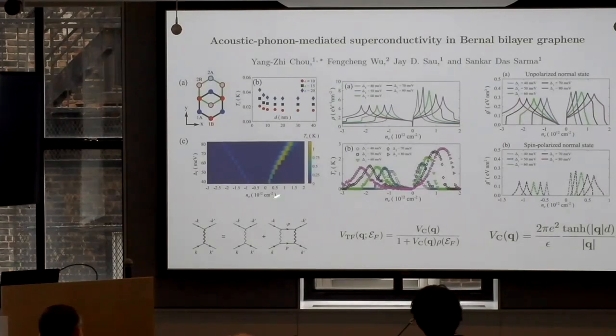Here, with Tc being this low, I insisted that we must include the mu star effect, meaning the repulsive interaction effect. First, there is a screening effect just coming from the gates. You have gates, so this is just the undergraduate image charge effect. You can derive this formula, because there are many image charges, there are two gates, and you immediately find the actual Coulomb interaction, 1 over q, is suppressed by tanh(q) over q.